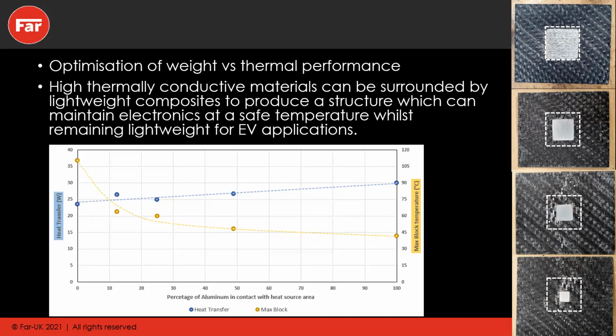The pictures of the coupons on the right-hand side of the screen show different amounts of embedded aluminium. So starting from the top, it's 100%, 50%, 25%, and 12.5% of the heat source area. The heat transferred, we perform the same experiment and plot the results. And as we expect, the heat transferred is linear to the amount of aluminium in contact with the heat source. And this results, which is the blue line, and then this results in a lower heat source temperature, which is the yellow line.